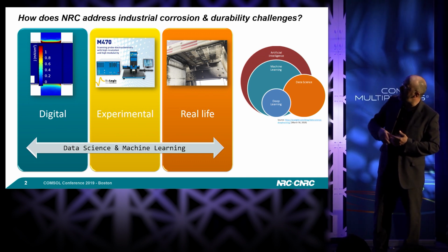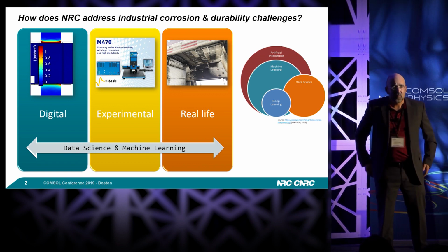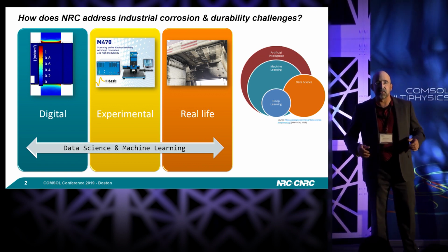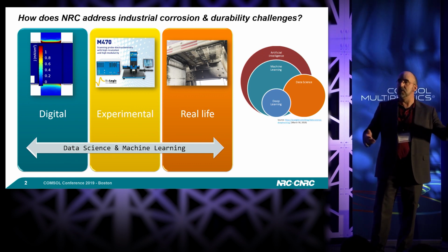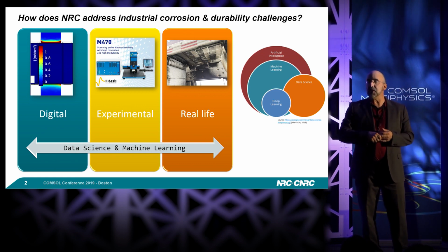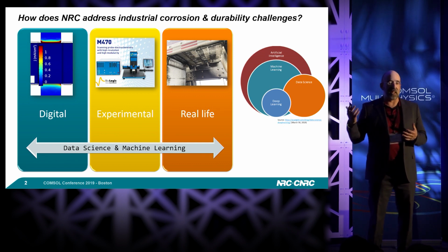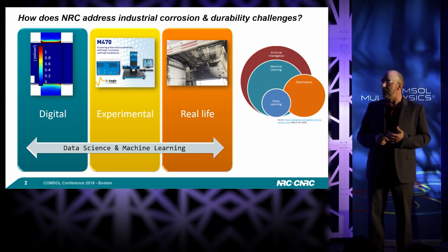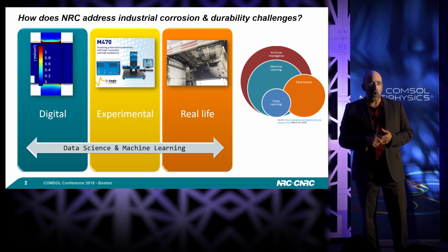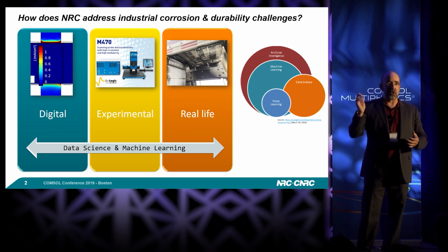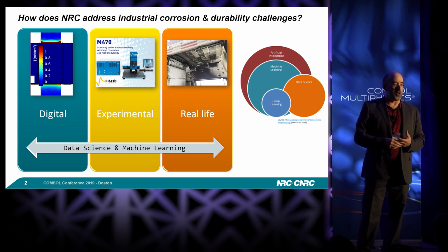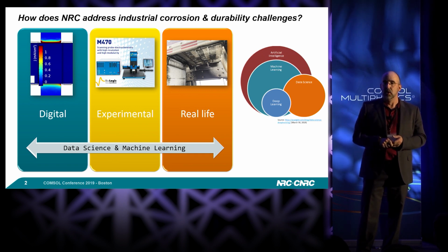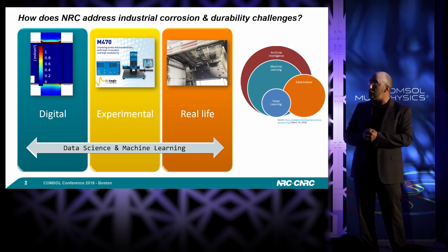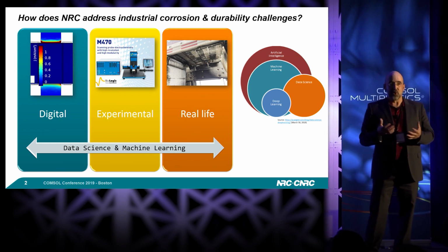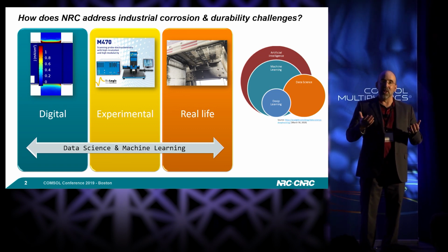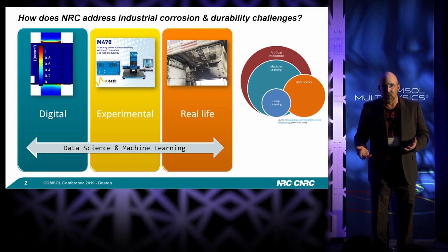Then you go more on the left, the experimental side. Here you have tests such as salt spray, the famous ASTM B117, or each standard organization has a standard which is the equivalent of this B117. You put your sample in a corrosion chamber. You have a salt spray, 35 degrees C, 5% sodium chloride for 1,000 hours. Then you remove your samples and you look at them and you try to draw some conclusion. But can you rely on this test to understand what is happening on the road?